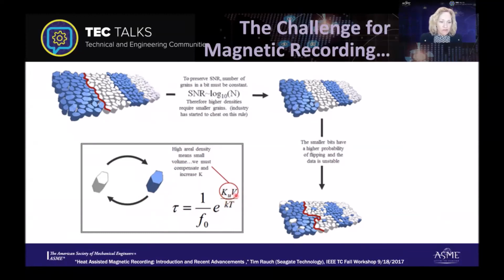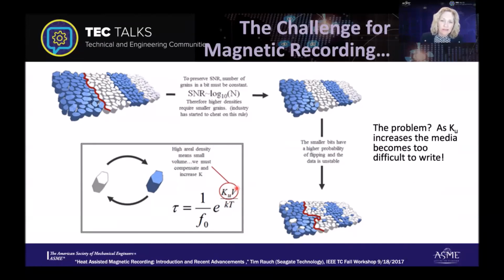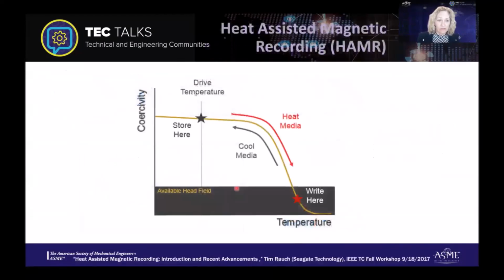And so as you scale the grain down, scaling down the volume, this is related exponentially to the volume and this resistance to flipping the magnetization. And so as we make the volume of the grain smaller, we need to increase that resistance to flipping the magnetization. But the problem is, as we do that, it is also the resistance to changing the magnetization with the writer's field. And so it makes it more and more difficult to write. In fact, we may get to the point where it's beyond where we have enough field to be able to write.